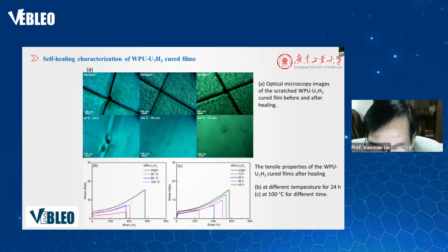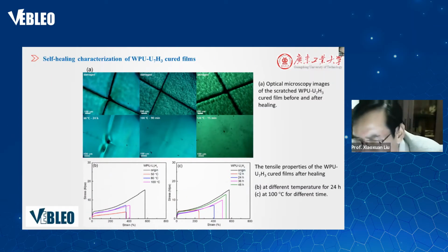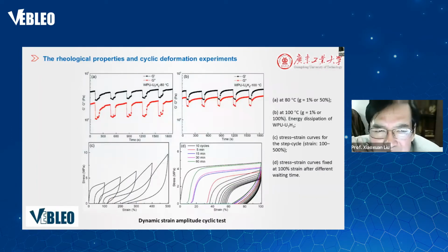Next, the tensile properties of the WPU film after healing. Figure B is at different temperatures for 24 hours. C is at 100 degrees for different times. This is the rheological properties of the cyclic deformation experiment.